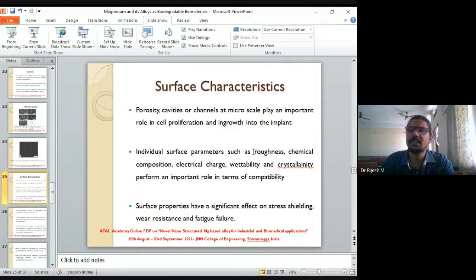Individual surface parameters such as roughness, chemical composition, electric charge, wettability, and crystallinity play an important role in terms of compatibility. This is important because when your material is rough, the contact area is much more. The chemical composition, yes, we have just seen that instead of pure magnesium, if you go for a magnesium calcium, the corrosion rate is less. Depending upon the electric charge, the wettability. Wettability plays a very important role because if the body fluid is not wetting, then we will not have any interactions.